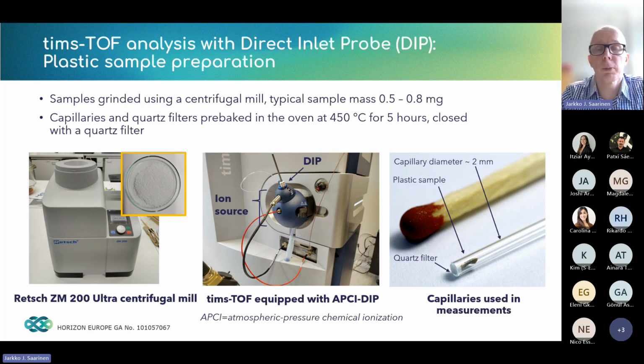So how do we do the typical setup for the measurement using the direct inlet probe with the atmospheric pressure chemical ionization tools in our timsTOF device? As Mathilde said, the representativeness of the samples, especially in the case of recycled plastics, can be difficult. So what we have been doing is grinding the polymer samples using a centrifugal mill. The typical sample mass that we use in our measurements is roughly 1 milligram.